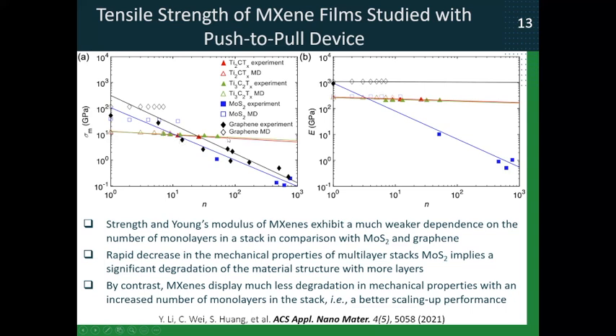It also happens in case of MXene, but at much slower rate. As you see, these curves, which are for titanium 2C and titanium 3C2, are much more horizontal. So that means that strength and Young's modulus in MXene stacks is maintained much better compared to other materials, graphene or molybdenum disulfide in this case, which means that MXenes show better scaling up behavior compared to other materials.